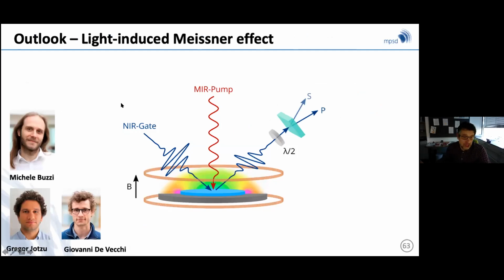So, outlook. This is, again, work led by Gregor, who came up with this conjecture where the next step is really to probe whether a magnetic field is being expelled in these systems. And of course, what you need to find is a way to measure a magnetic field at the surface of this material in equilibrium, both in the metal and in the superconducting state, and also in the light-induced state. And what Gregor is working on together with my excellent student, Giovanni De Vecchi, who's leading this, and Michele Buzzi is also helping out, has been to put a magneto-optical material like a garnet slapped on top of the